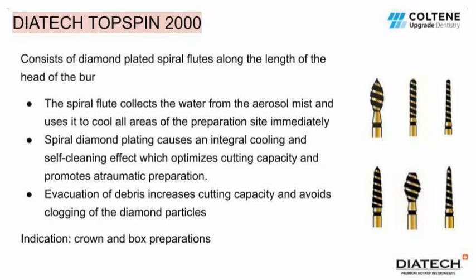Coming to DIATECH TOPSPIN 2000. The burrs consist of diamond-plated spiral flutes along the length of the head of the burr. These spiral flutes collect the water from the aerosol mist and use it to cool all areas of the preparation site immediately. The spiral diamond plating causes an integral cooling and self-cleaning effect which optimizes cutting capacity and promotes atraumatic preparation. The evacuation of debris increases cutting capacity and avoids clogging of the diamond particles. These burrs are primarily indicated for crown and box preparations.